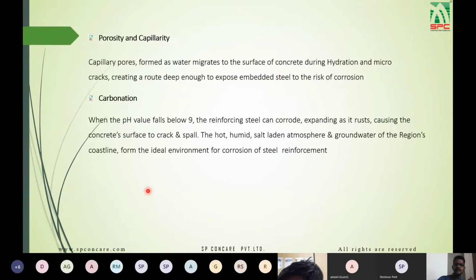So next is porosity and capillarity. Now, when you add the excess water, it leaves capillary pores formed as the water migrates to the surface of concrete during hydration. These micro cracks create a route deep enough to expose embedded steel to the risk of corrosion. So if water molecules or any other chemical or substance which can cause the reinforcement to corrode enter, this is the major way for that to happen.